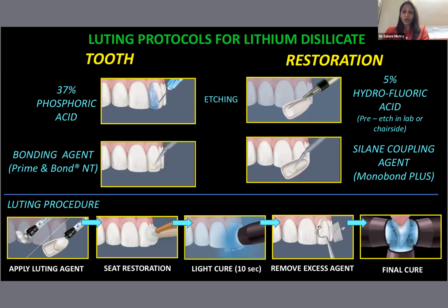Absolutely. Yes, it does. Zirconia does cause the wear of opposing tooth. That's what exactly I said, that it's very, very important for us to judiciously use zirconia. Primarily zirconia is supposed to be used with layering. So lithium disilicate is softer and kinder to the opposite dentition. So that's how using monolithic zirconias or just pure zirconias are not the preference of choice. As I said in one of the earlier questions also, with BruxZir, when you're talking about reconstructing absolutely all the posterior zones, when you have upper BruxZir crowns, lower BruxZir crowns, and you have